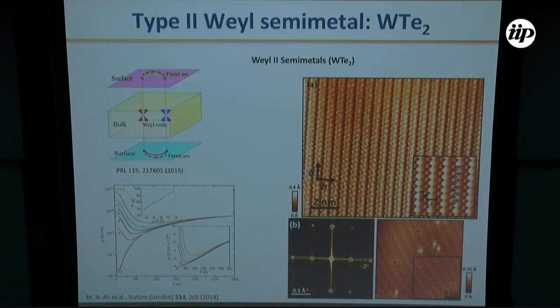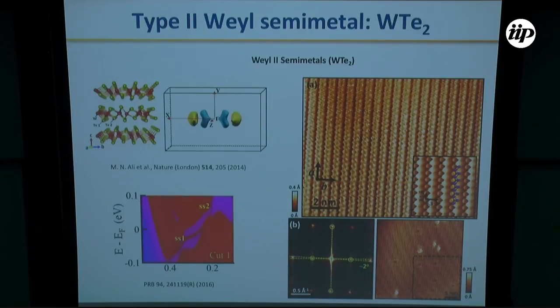And here I want to show you some preliminary results that we have obtained in the type 2 Weyl semimetal tungsten ditelluride, where we have obtained information not only from the surface band structure, but also from the bulk band structure. Essentially, in this material, we have a bulk electronic structure with Weyl points. And at the surface, we have the projection of these points, which are connected by open Fermi surfaces, known as Fermi arcs. So we have made a QPI study in this material.